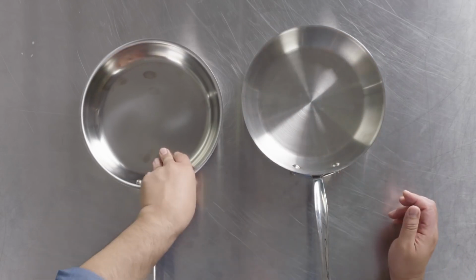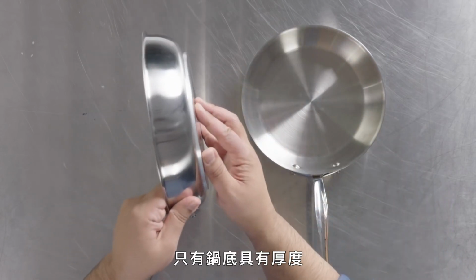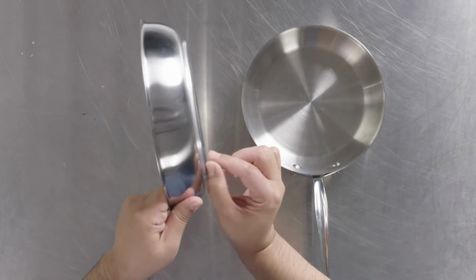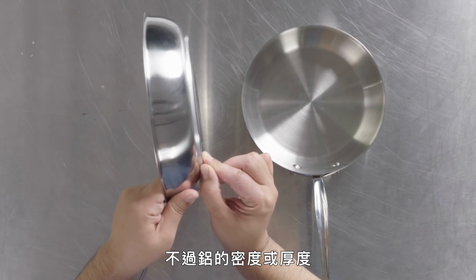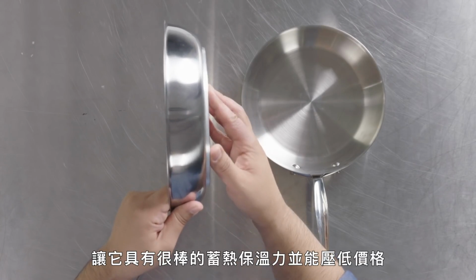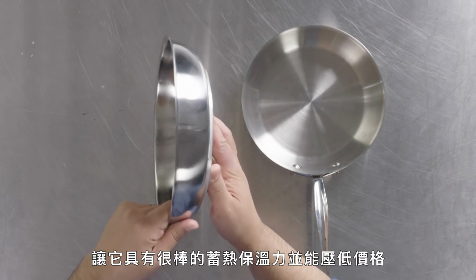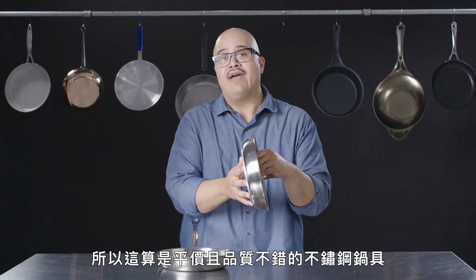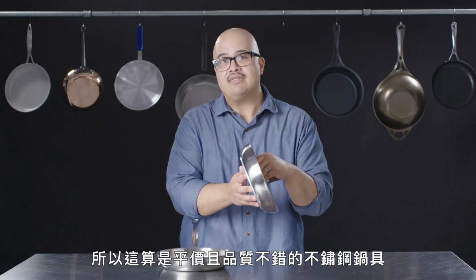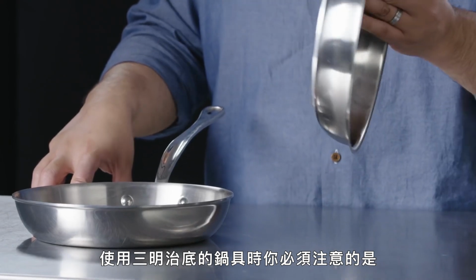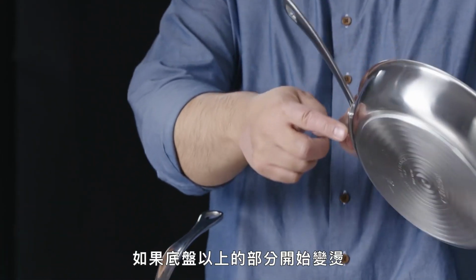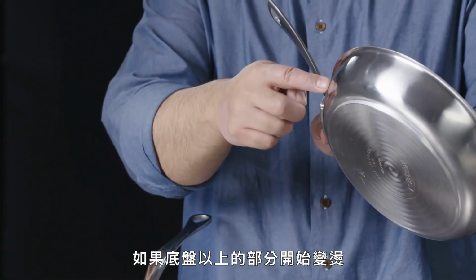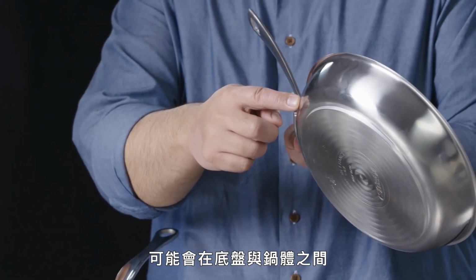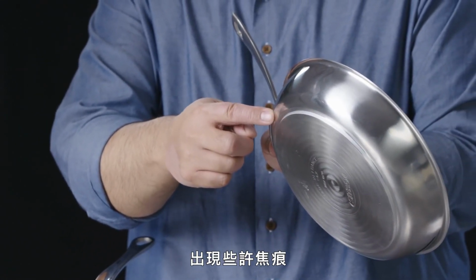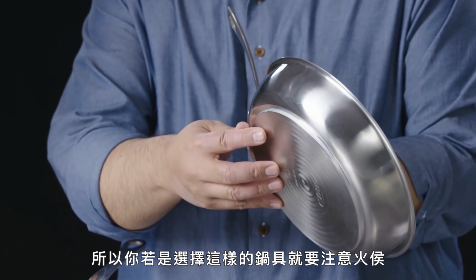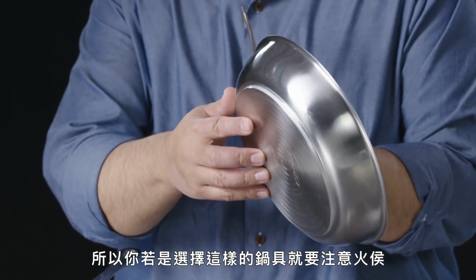There's no variation. In a sandwich bottom, the thickness is just here at the base. But that density of aluminum or that thickness allows for great heat retention and also lowers the cost of a pan. So it's kind of an economic or a good value point for a quality stainless piece. The one thing that you have to be cautious of in sandwich bottom construction is if you begin to send heat beyond the disc, you may experience some scorch between that disc and the actual pan itself. So be careful to control your flame if you elect to buy this style of cookware.